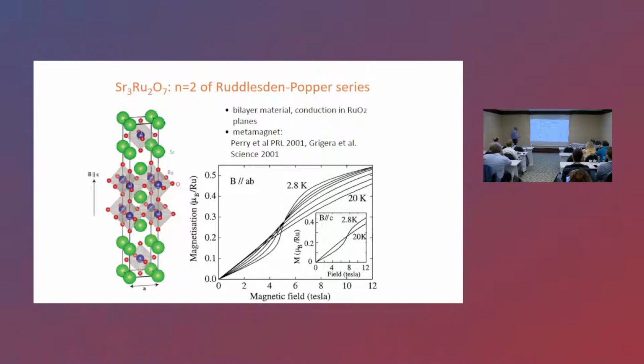Early, it was discovered to be a metamagnet, especially if we focus on magnetic field along the C-axis. This is around 8 Tesla, the metamagnetism, but it's not a simple metamagnet. If you deviate slightly from the C-axis with the magnetic field, there is a strong anisotropy in resistivity along A and B direction. And people think that nematicity is a new order that plays a role, etc.